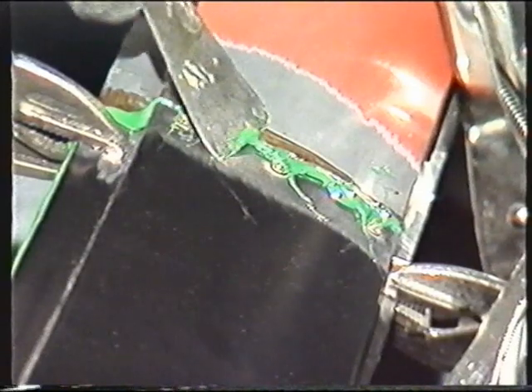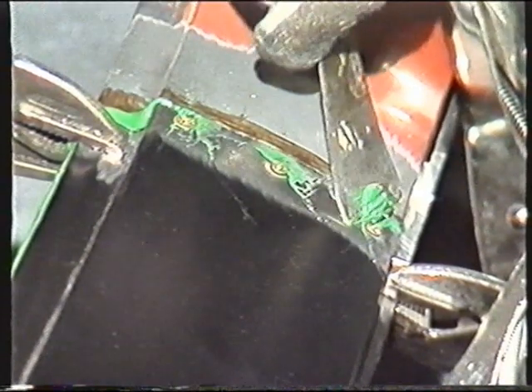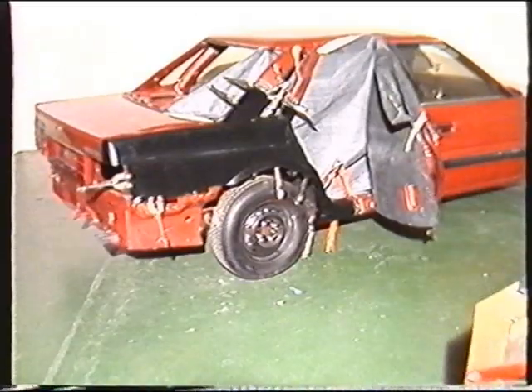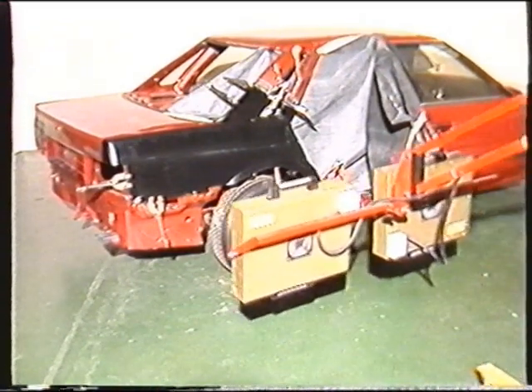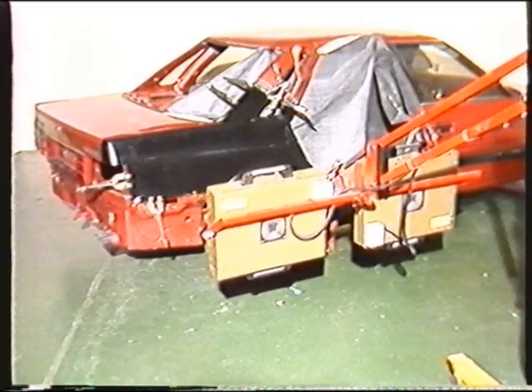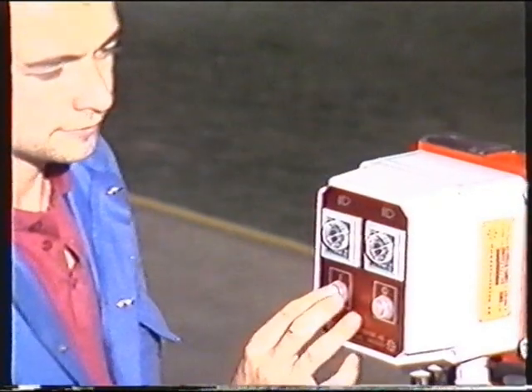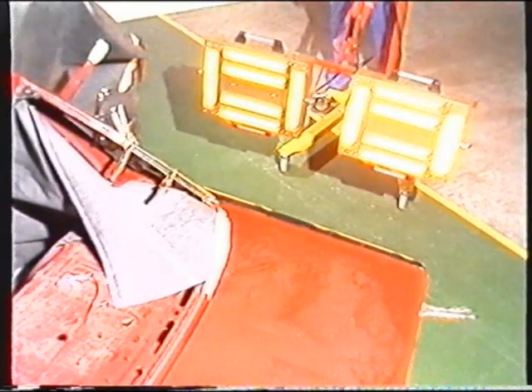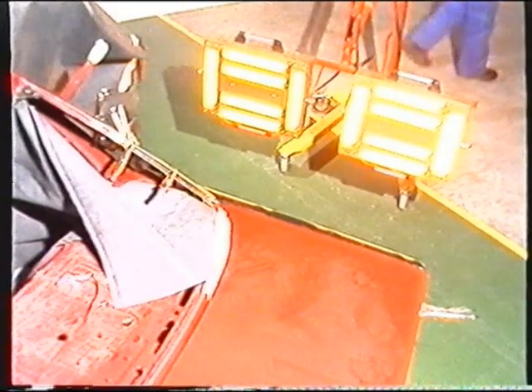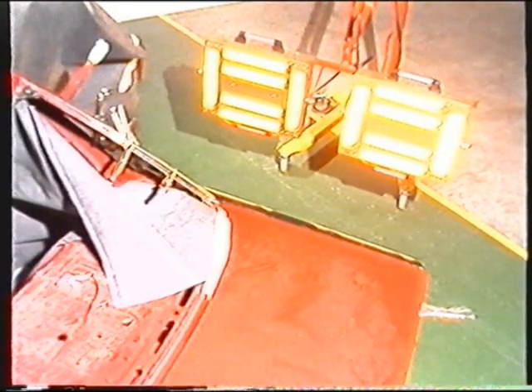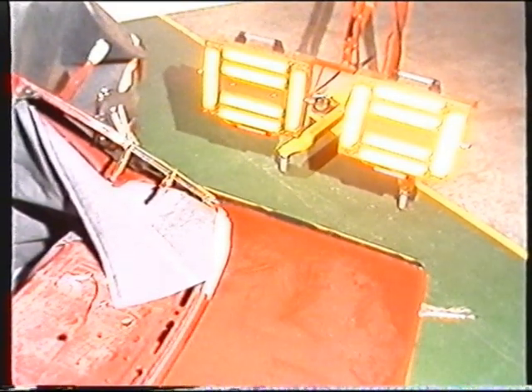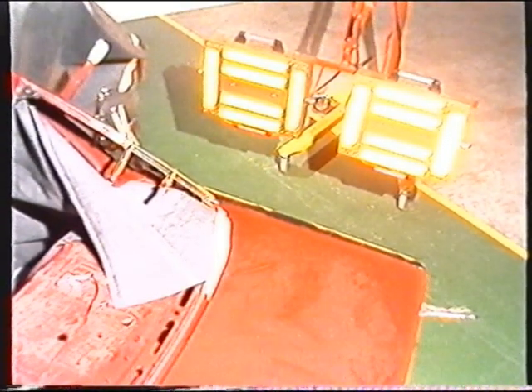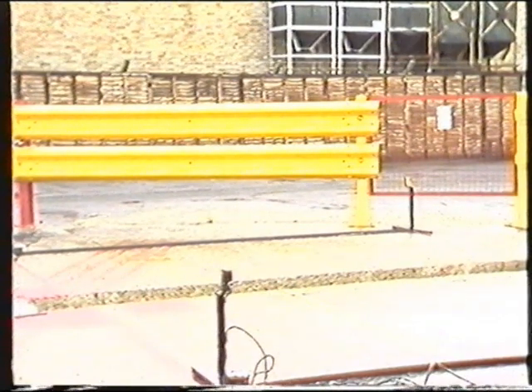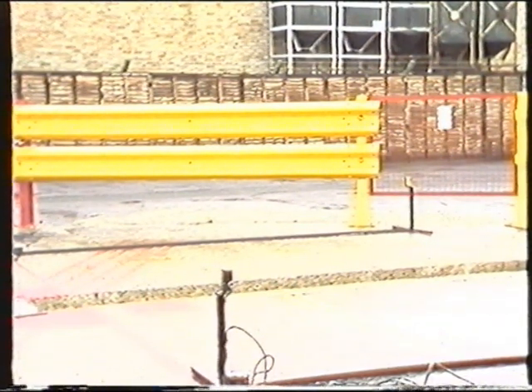Finally, any excess adhesive is removed. Curing is best carried out at a metal temperature of 40 degrees centigrade for 1 hour. Most 2-part epoxy resin structural adhesives will not reach full tensile strength if heat isn't used. Additionally, adhesives cured without heat may reactivate when subjected to paint oven temperatures. For the time being, however, adhesives should only be used during repair where recommended by the manufacturer.